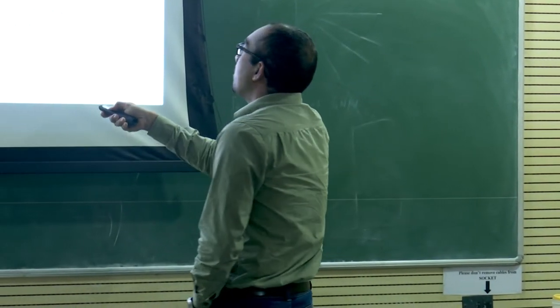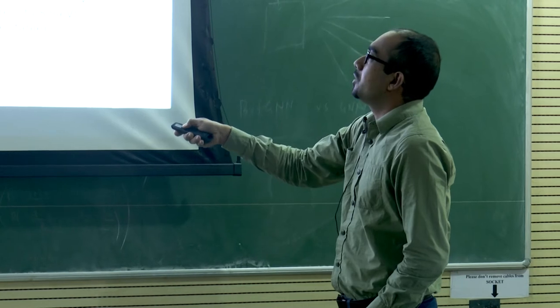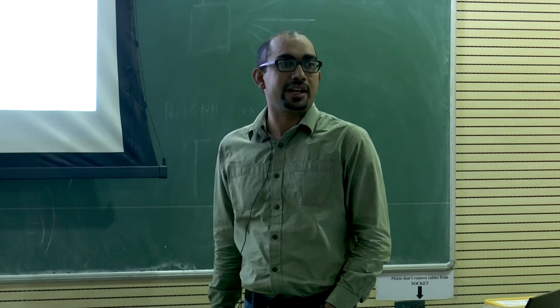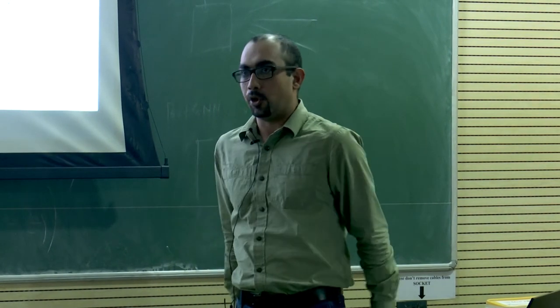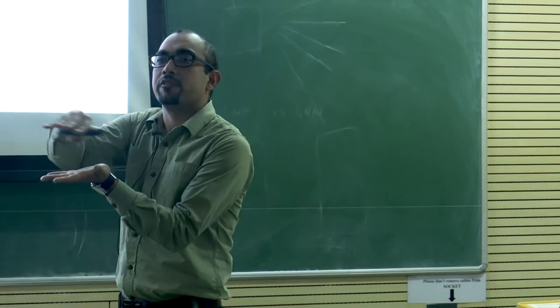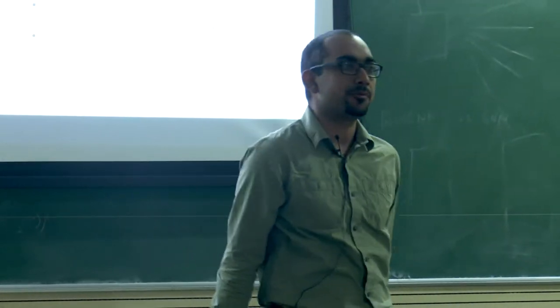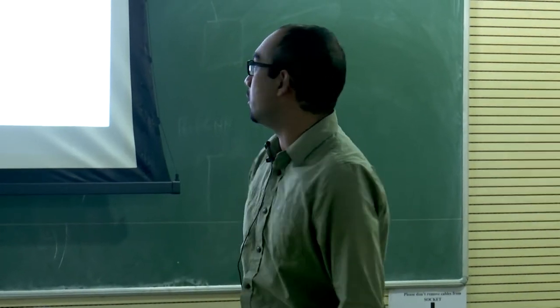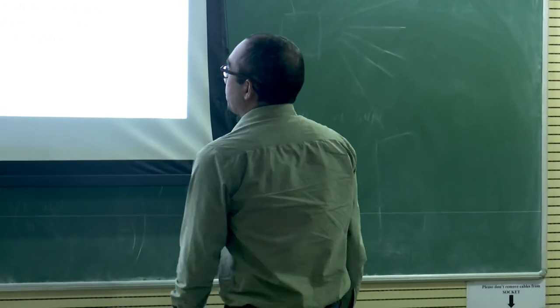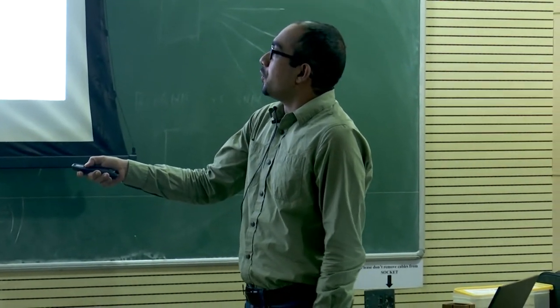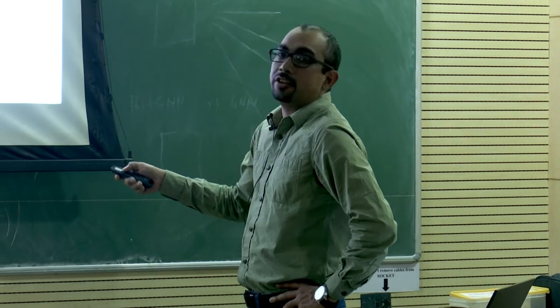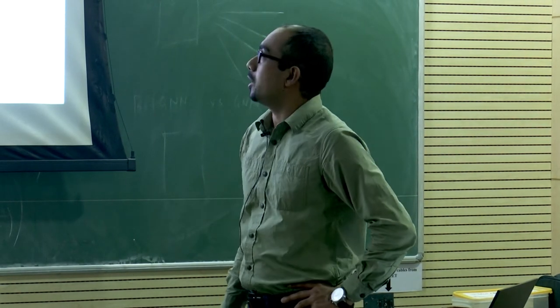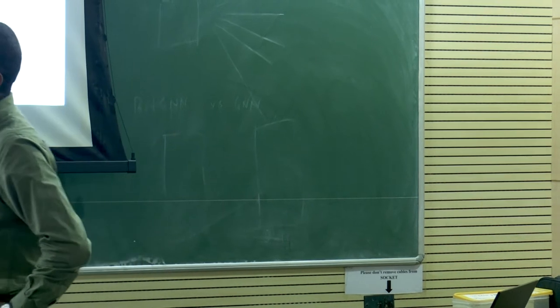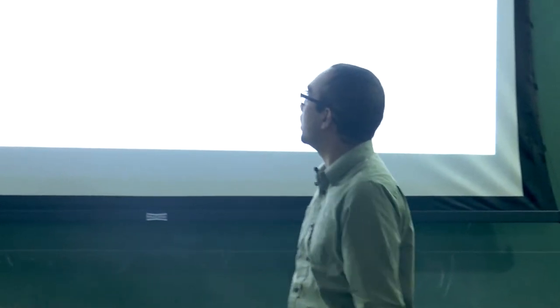However, in the two-dimensional case, it turns out that the binding energy is theoretically four times that of the 3D case. So the exciton is strongly bound. It's strongly bound because now you have confined this exciton. So this is the physical reason behind this strong binding of excitons in two-dimensional systems. I want to say that the excitons strongly modify the absorption spectrum. Let me tell you how. For absorption-based devices, this is very important to understand.